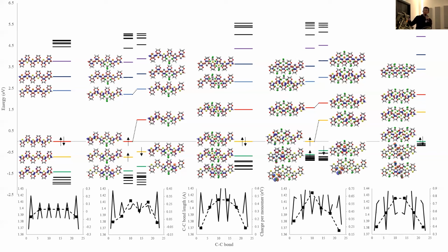So in fact, what you've actually got is really quite a conventional system where as you remove electrons, you just move down to the next state and you're not creating new states. The closest you get to seeing the new states is you get to see the non-bonding orbitals of the anions starting to feature around the gap when the concentration of anions builds up enough to push those orbitals up towards the gap.